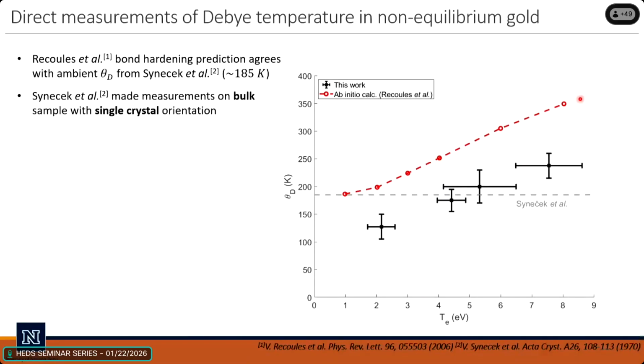So we spent a long time thinking about this, and eventually we decided it's because our system is already quite weak at room temperature, because this prediction here is for single crystal gold, so bulk single crystal gold. But we had polycrystalline gold with extremely tiny grain sizes. Grain size of the order of nanometers, I think. And so what that means is that our system is already weak to begin with.